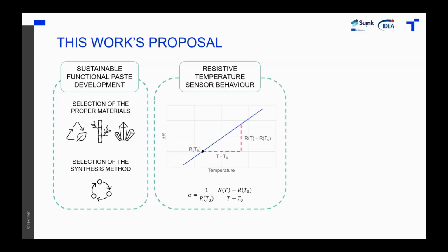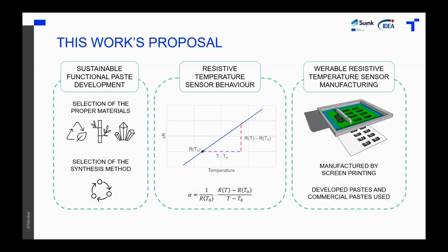We thought about developing sustainable functional inks by selecting bio-based materials, selecting properly the synthesis method, and optimizing them. Then we decided to develop resistive temperature sensors, because a resistive temperature sensor modifies its resistance with temperature, and we could characterize them by the temperature coefficient of resistance. We decided to make wearable resistive temperature sensors by screen printing. In this case, we will print the sensor onto fiberglass, because we have a certain application that needs this substrate, and it is also flexible.